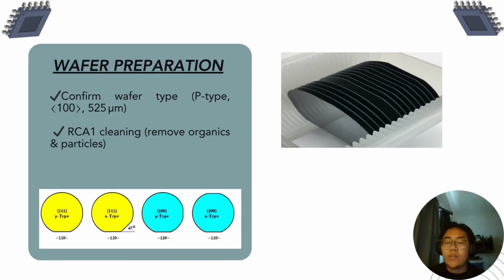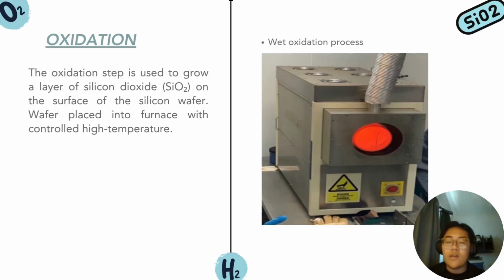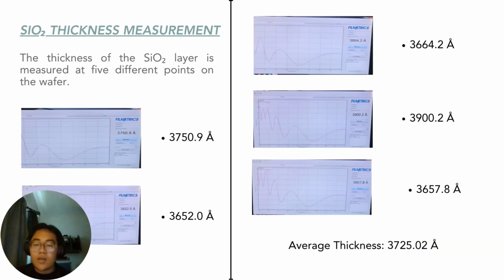We're using a P-type substrate. The orientation is 100, and the thickness of the wafer is 525 micrometers. We're using RCA1 cleaning to remove particles on the wafer. Next is the oxidation process. We place our wafer into the furnace at a controlled high temperature to grow silicon oxide. We measure the silicon oxide thickness at 5 different points and got an average of 3725 angstrom.